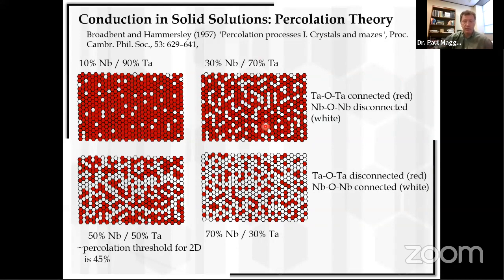So here are basically four diagrams. One with 10% niobium, 90% tantalum, where niobium is in white, tantalum is in red. And you can see at this amount, randomly distributed, niobium is just isolated. You go up to 30%, you can see there's a much higher connectivity. Here's four niobates connected together. Here's a much larger cluster connected together, but you haven't hit that threshold for extended connectivity from one end of the crystal to the next.